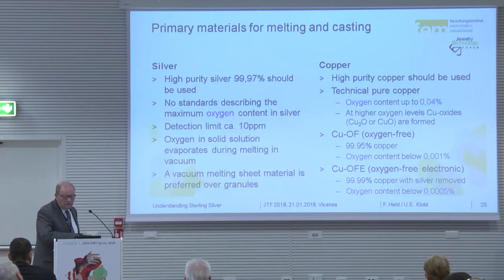Copper, you should use high purity copper. On copper, we have different hallmarks for the oxygen content. You use technical pure copper, oxygen-free copper, or oxygen-free copper electronic. You see here you have 0.04 percent oxygen in copper. If you use oxygen-free copper, you only have 0.001%, and if you use oxygen-free electronic, you have 0.0005% oxygen. This is the best quality you can use, and the result is clear.